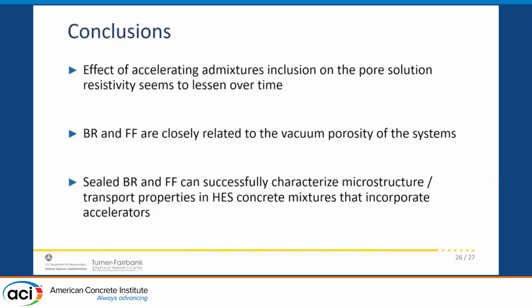We saw very good correlation between bulk resistivity and porosity, which is promising for further studies on correlating these to transport properties. And again, the microstructure features that we measure were pretty well correlated with these test measurements.